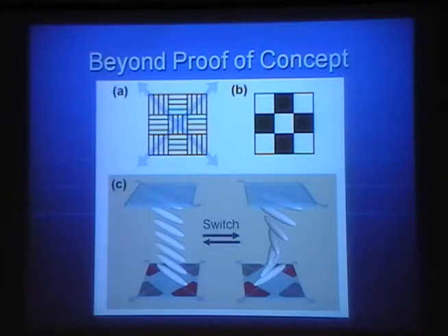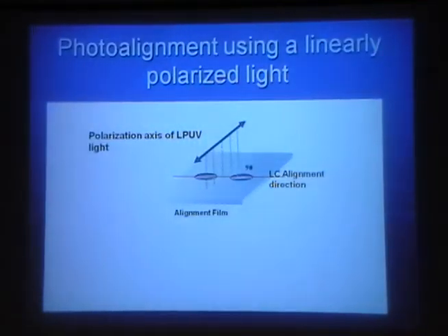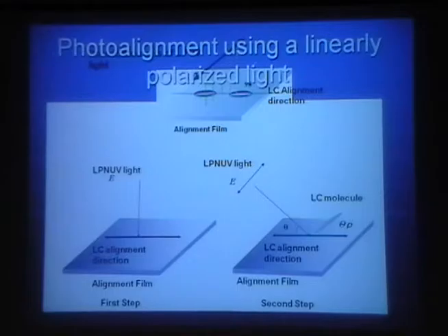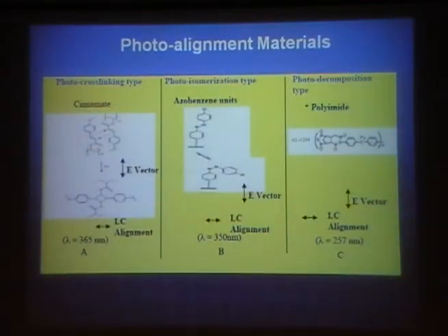Instead of using atomic force microscope, we started using photo alignment, and we created a checkerboard pattern, using primarily azo derivative molecules as surface alignment layers.